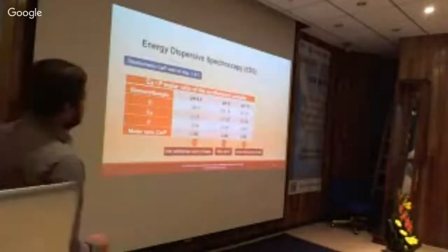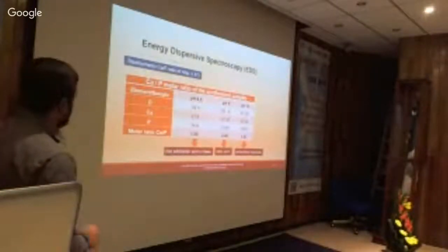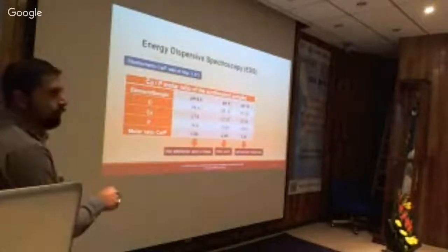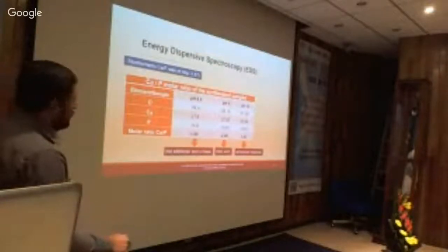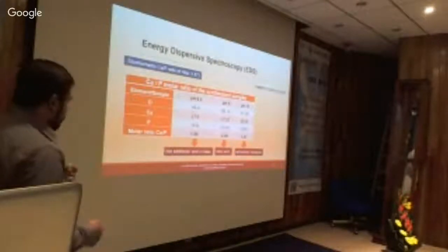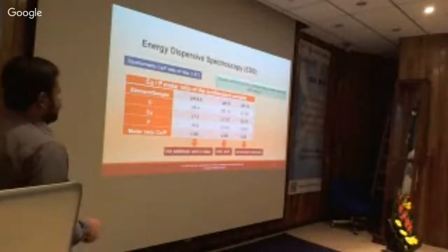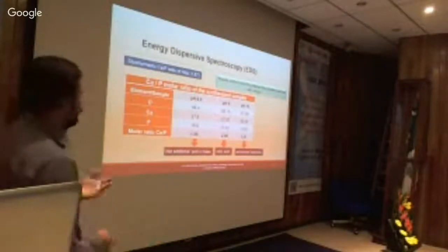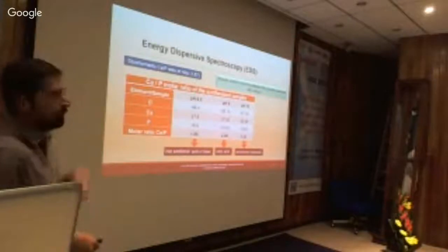So, EDS analysis. To confirm the calcium to phosphate ratio, a stoichiometric hydroxyapatite should have a calcium to phosphate ratio of 1.67. In each case it is more than this, so there is more abundant calcium. So obviously calcination is necessary, a compulsory process, to evaporate the calcium part, reduced due to